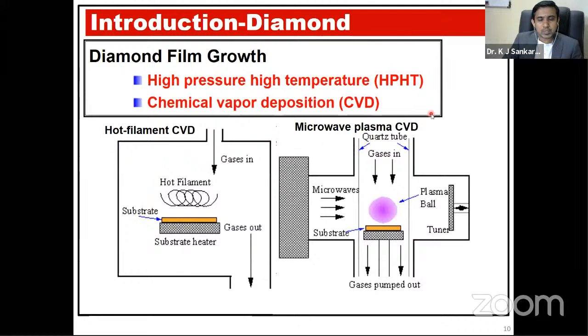But when you go to the microwave plasma CVD, it needs a very low pressure and also a very low temperature, because when you inject the microwave into the system and pass the gases, this microwave reacts with the gases and makes some species, that is reactive species, ionic material or radicals, that form a plasma ball. This plasma ball can react with the substrate and form a film on the substrate. So basically microwave plasma CVD is more advantageous than the hot filament CVD, because with the hot filament we need to replace the filament many times, even for one growth, if you are looking for very thick diamond films. So microwave plasma CVD is the best method compared to the hot filament CVD and other CVD techniques.